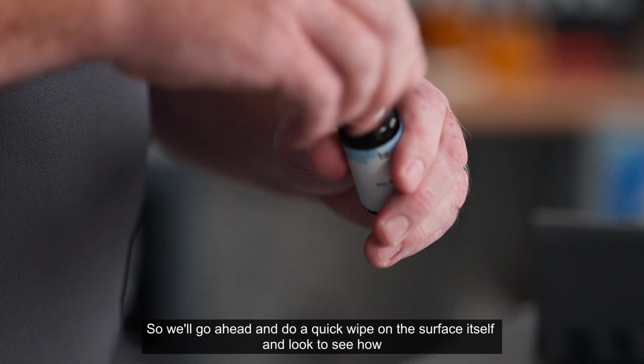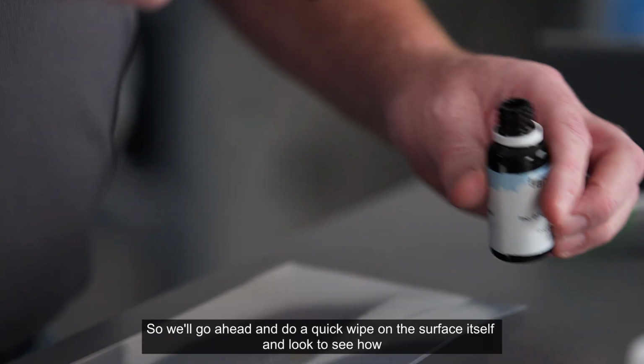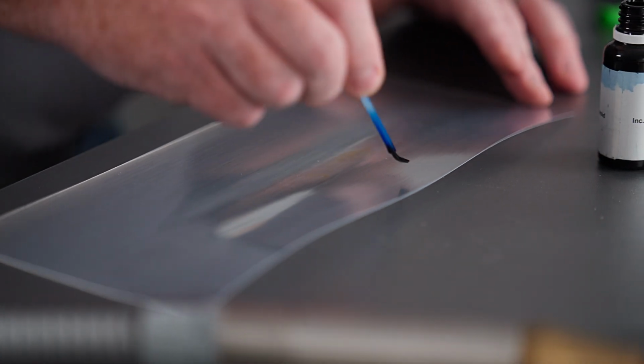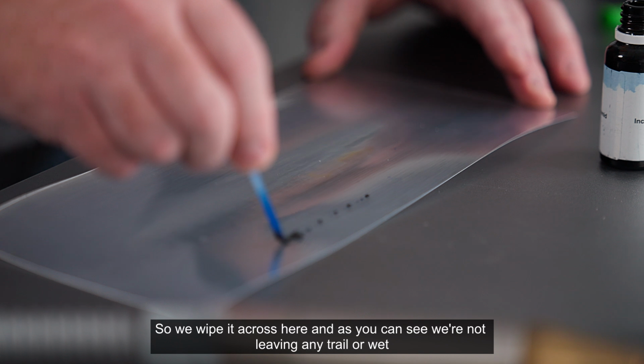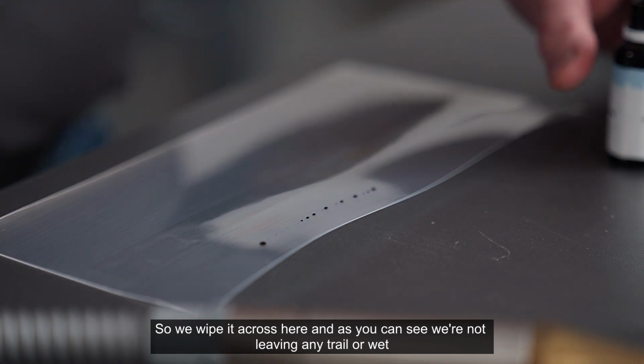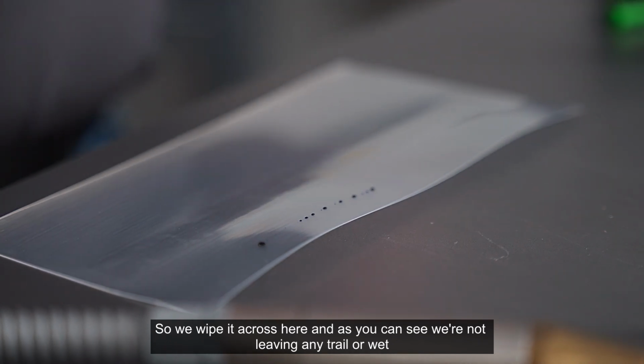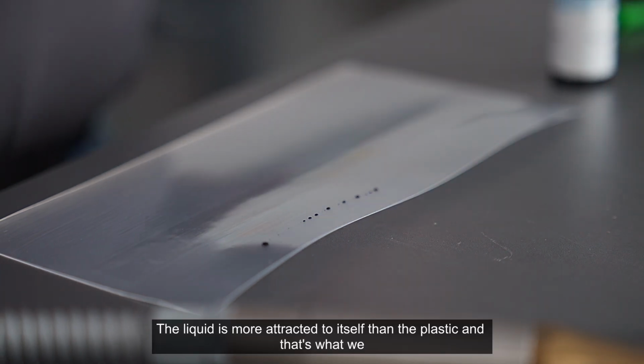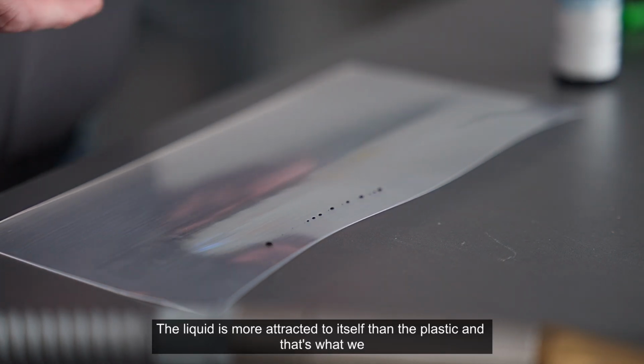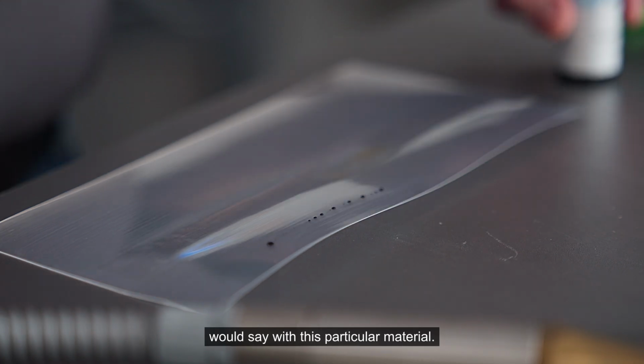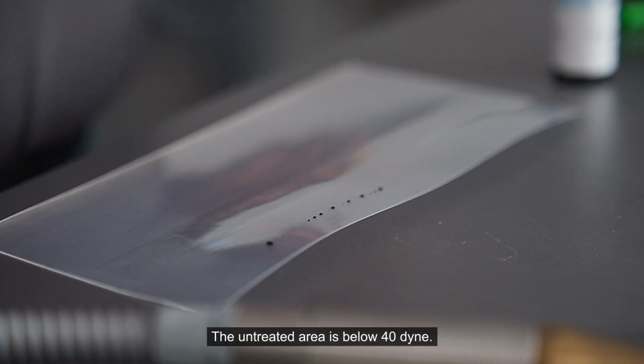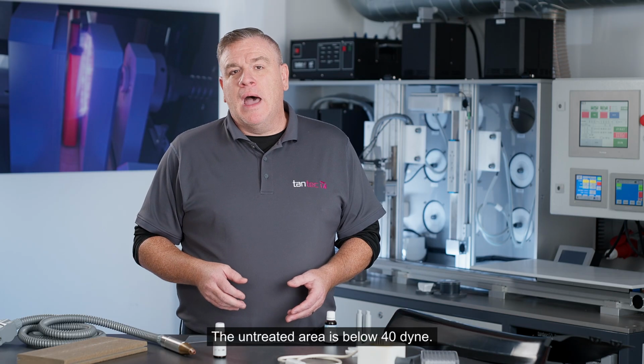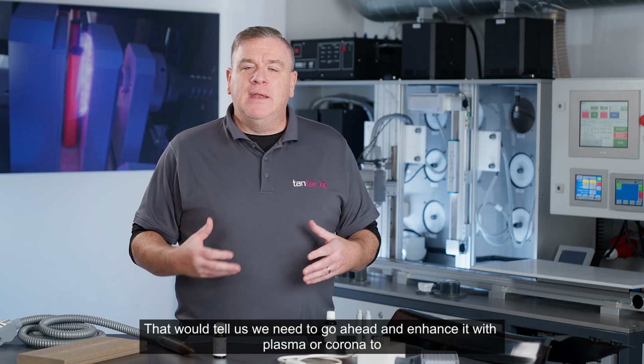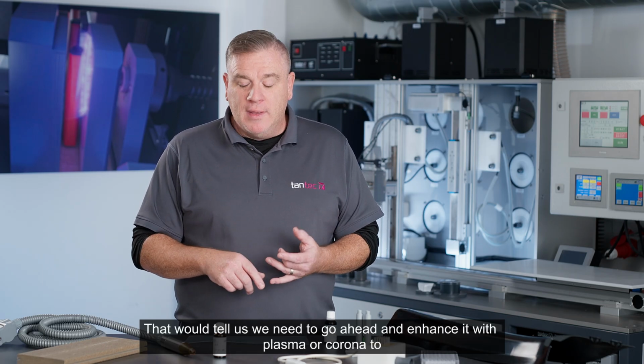So we'll go ahead and do a quick wipe on the surface itself and look to see how it reacts on the plastic. So we wipe it across here. As you can see, we're not leaving any trail or wet out of the surface. The liquid is more attracted to itself than the plastic. And that's what we would say with this particular material, the untreated area is below 40 dyne. That would tell us we need to go ahead and enhance it with plasma or corona to get that dyne level up.